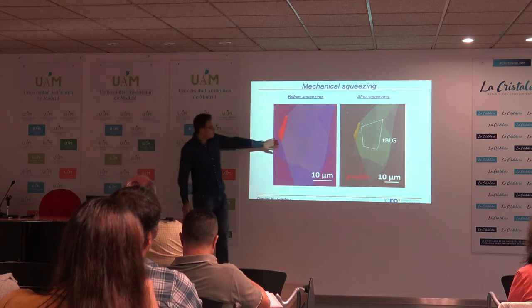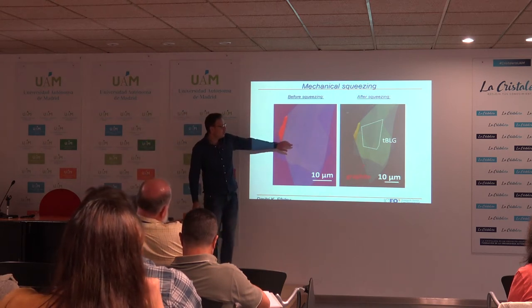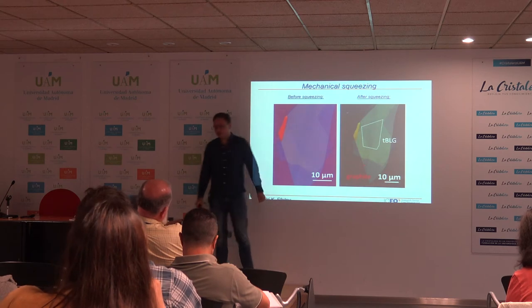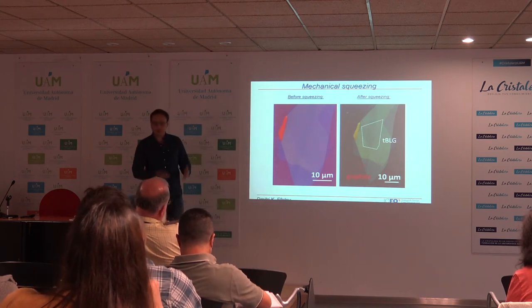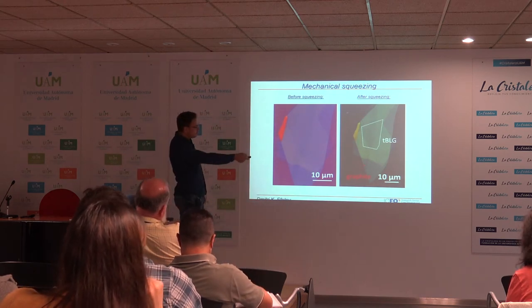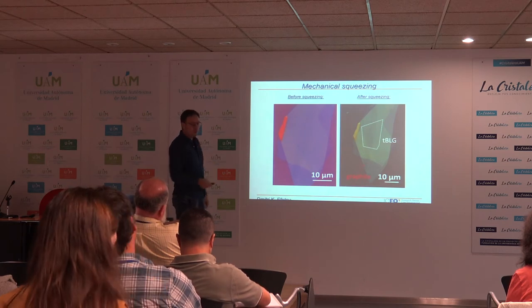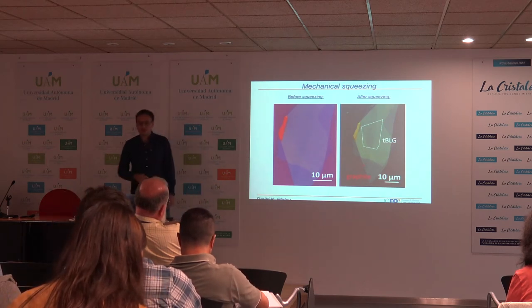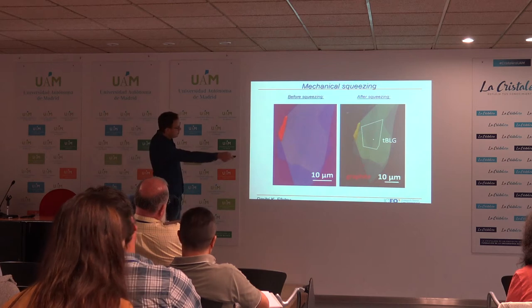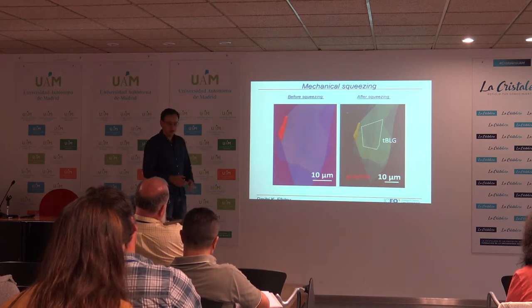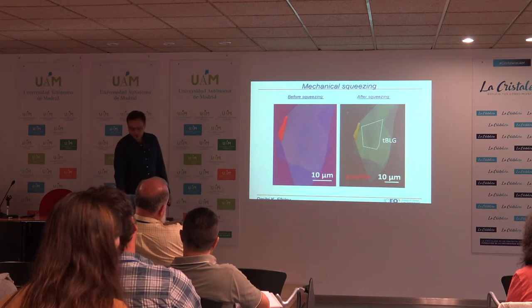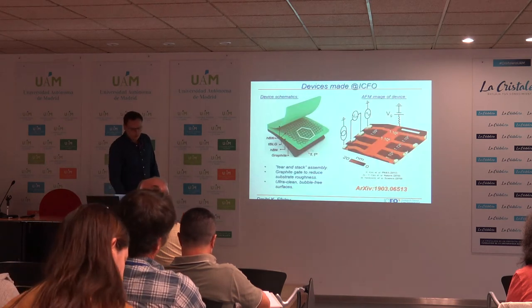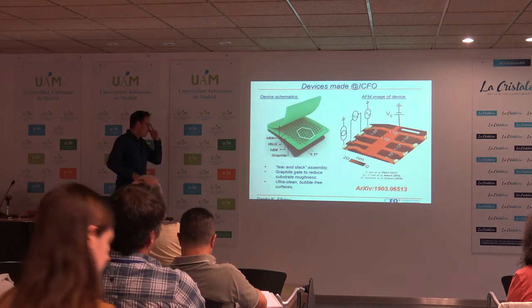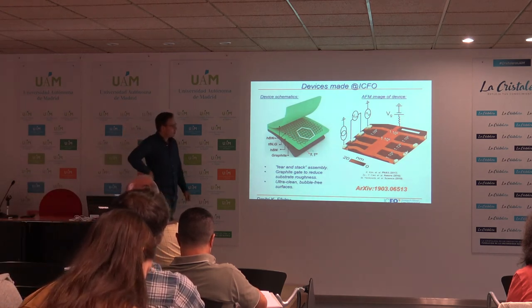And so this is a typical device image before, and this is a typical device image after we do this mechanical squeezing process. And you can see here, in the final device image, we don't see any type of bubbles. Maybe to the untrained eye not, but to the trained eye, this is definitely immediately a much, much cleaner device.